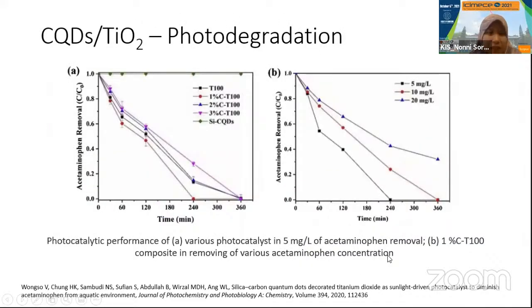So based on the performance to remove the acetaminophen, we found that the 1% addition of the carbon quantum dots into the titania gives us the most optimum results. After 4 hours under the sun irradiation, we can have a full degradation of the 5 ppm acetaminophen. So the material is still effective if we use it for higher concentrations of acetaminophen. For the 10 ppm of acetaminophen, it can be fully degraded after 6 hours. If it reaches 20 ppm, then we need a longer time for the material to perform the degradation process.